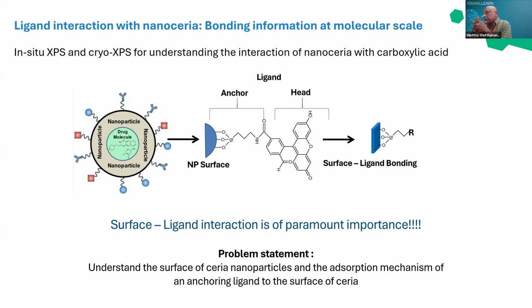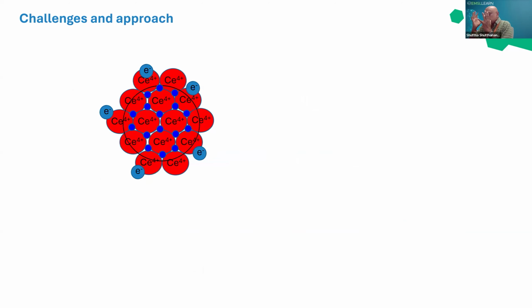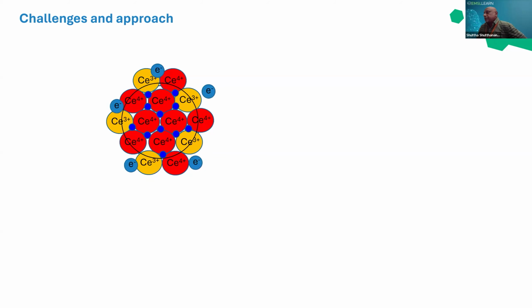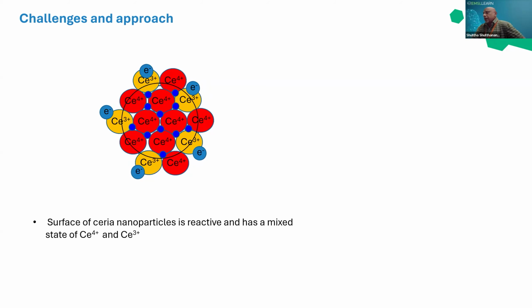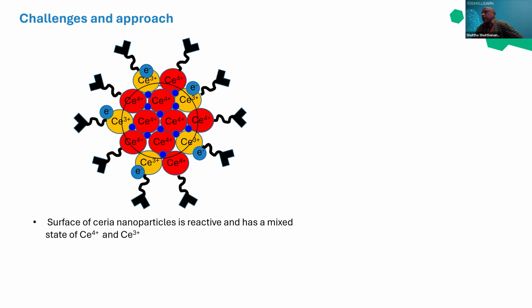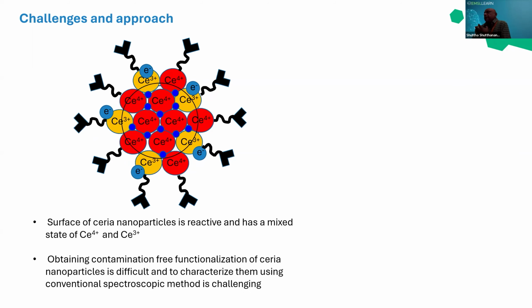We synthesized a model system of a cerium oxide (111) surface, which is fully oxidized, and then we anneal that sample in vacuum, and then we reduce the surface. Then we adsorb the carboxylic acid and study how these molecules are interacting with the cerium surfaces.